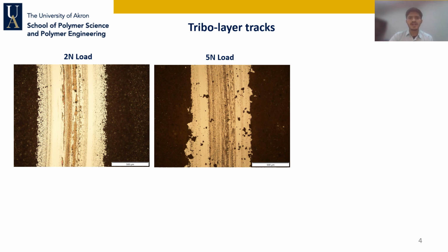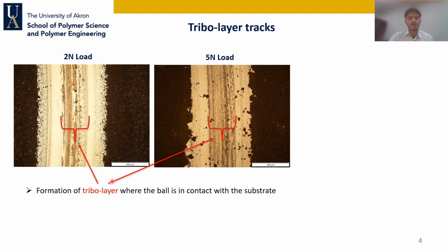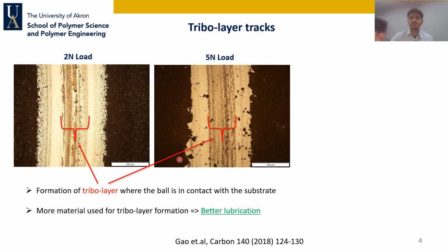So next we studied the tribo-layer tracks that were formed by the pin-on-disc measurement, and what we observed was that the tribo-layer formation took place where the ball was in contact with the substrate, and that was the expected result. But the more interesting result was that more material was used in the tribo-layer formation in the case of the 5 Newton load. So that again provided better lubrication, which we observed from the previous slides.